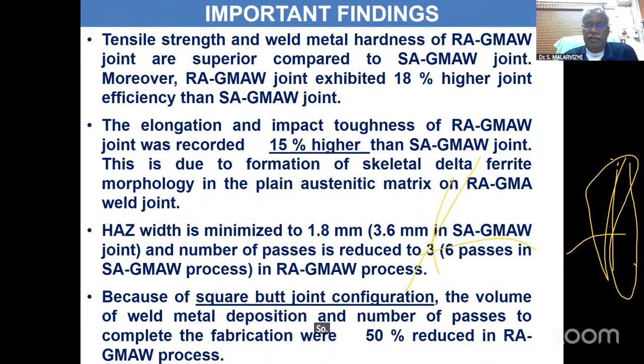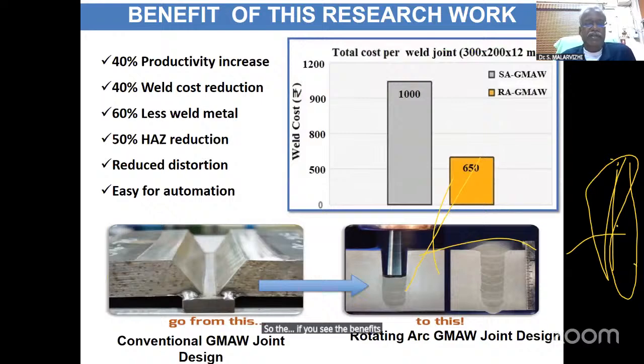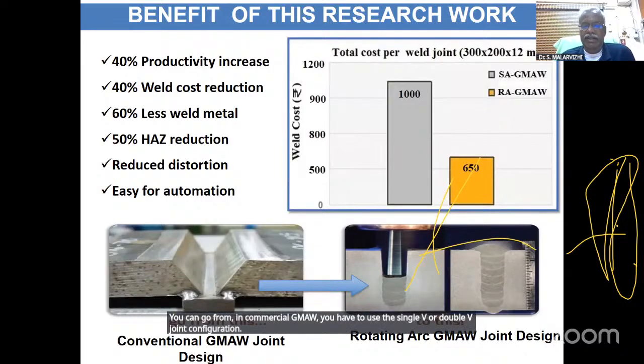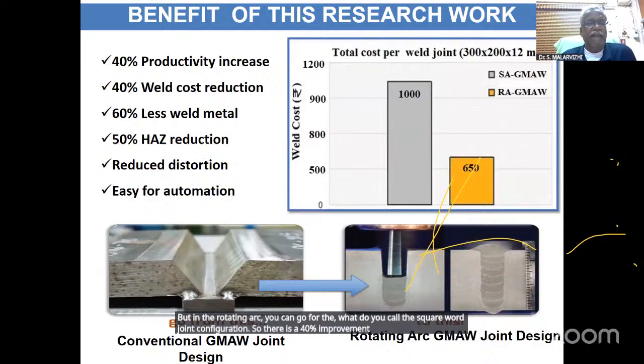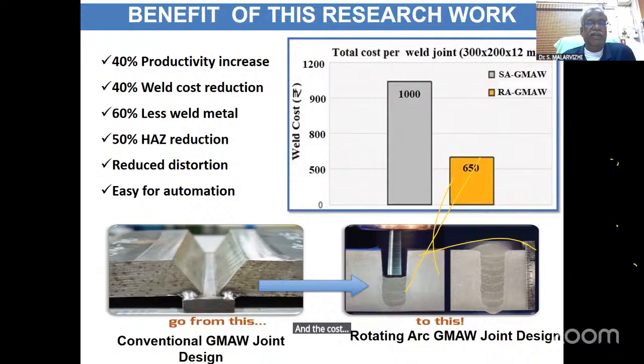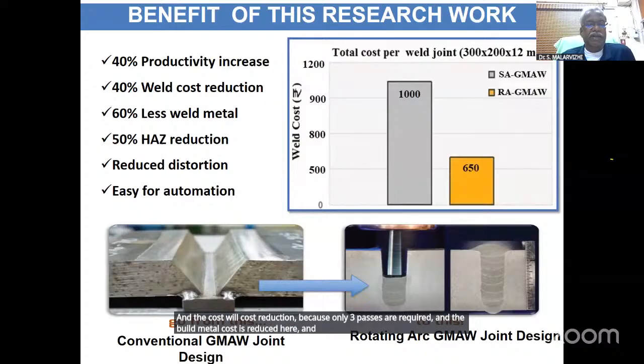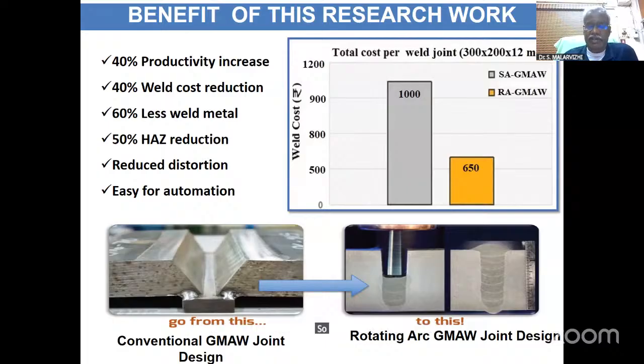So if you see the benefits of this process, in conventional GMAW, you have to use the single V or double V joint configuration. But in the rotating arc, you can go for the square butt joint configuration. So there is a 40% improvement in productivity and weld cost reduction, because only 3 passes are required, and less weld metal is utilized here. The width of the heat affected zone is also reduced, and finally heat input is low, so the distortion is also reduced. So these are the advantages of this process.